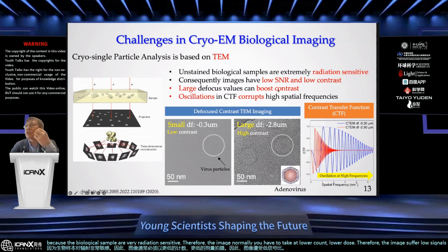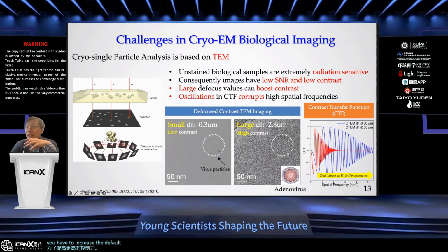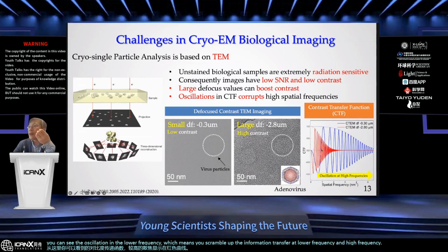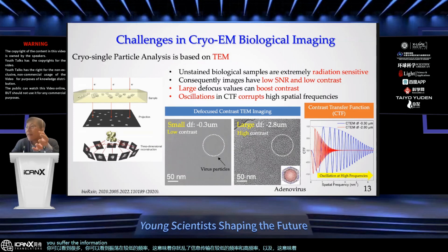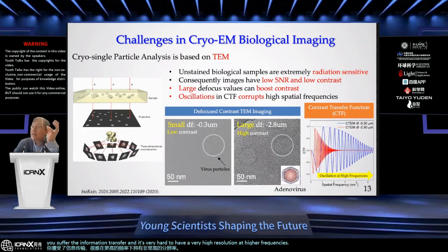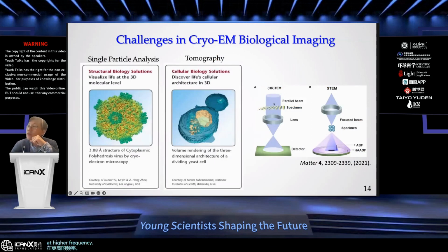In order to boost the contrast, you have to increase the defocus. For example, like here, if you want to see this virus particle. But as soon as you increase the defocus, from the contrast transfer function, as you can see here, with the higher defocus shown in the red curve, you can see the oscillation in the lower frequency, which means you scramble the information transfer at lower frequency and at high frequency as well. So which means you suffer in information transfer, and then it's very hard to have very high resolution at higher frequency. So that's what happens in TEM.